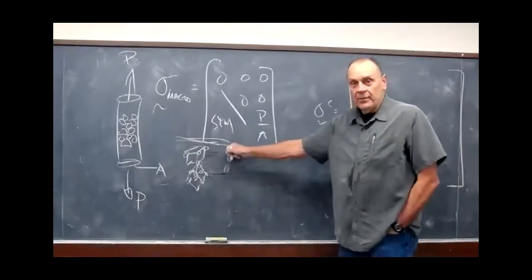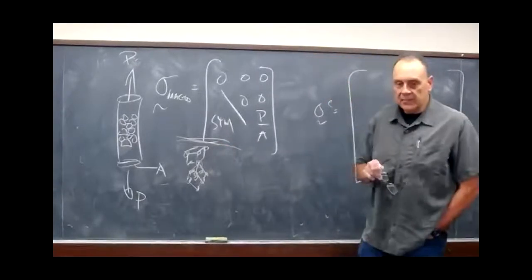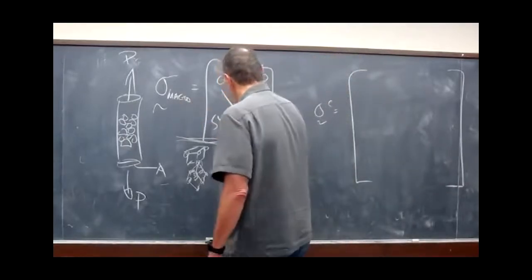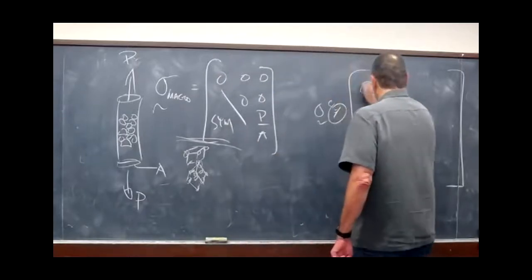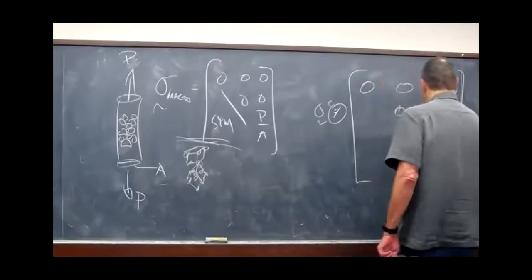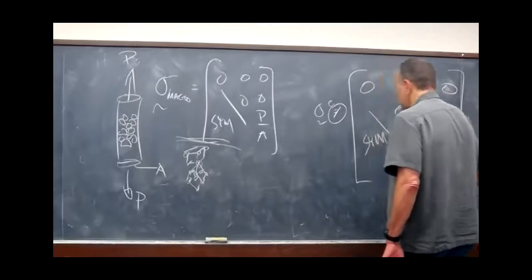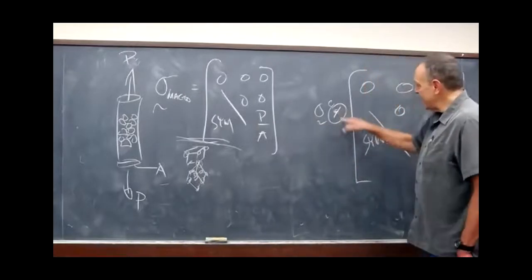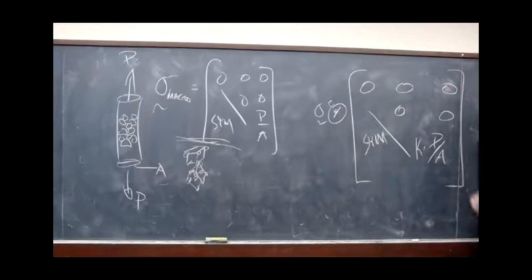This is a pretty complicated boundary value problem. And one of the first things that come out of these experiments is that sigma, at the crystal scale, you are not in P over A-ville anymore. For a polycrystal, it is not some multiplier times P over A. It'd be really unusual if it were.